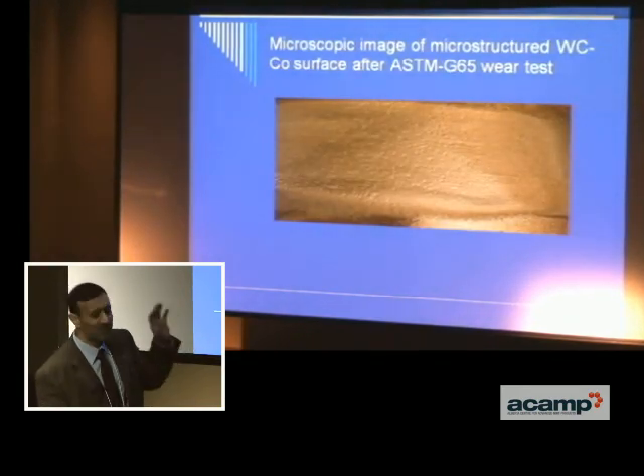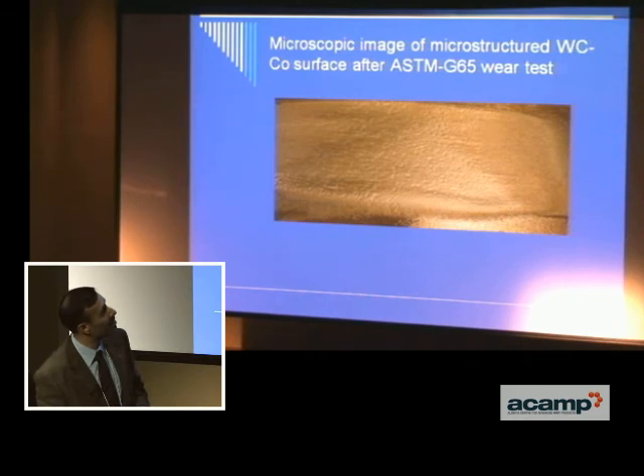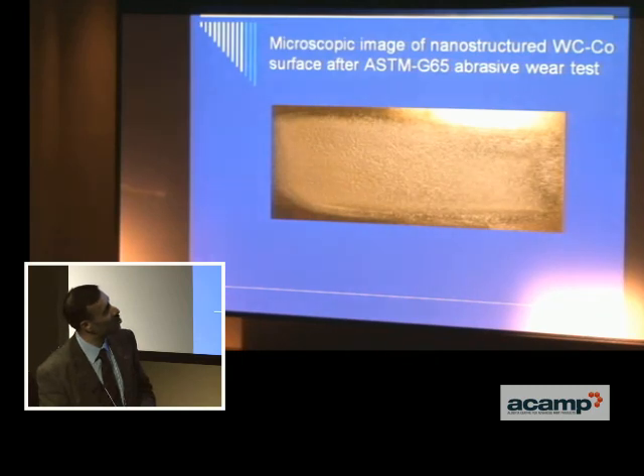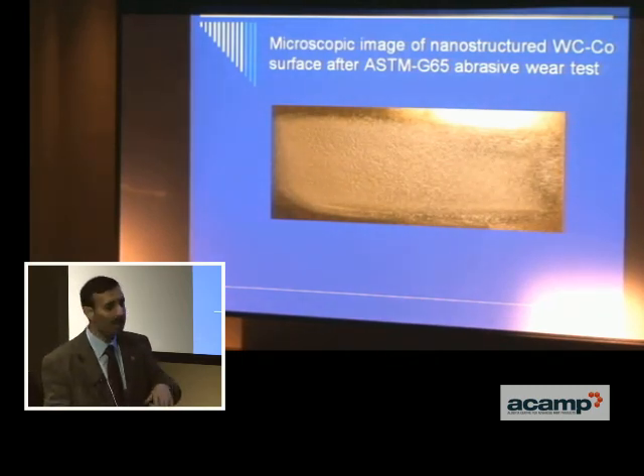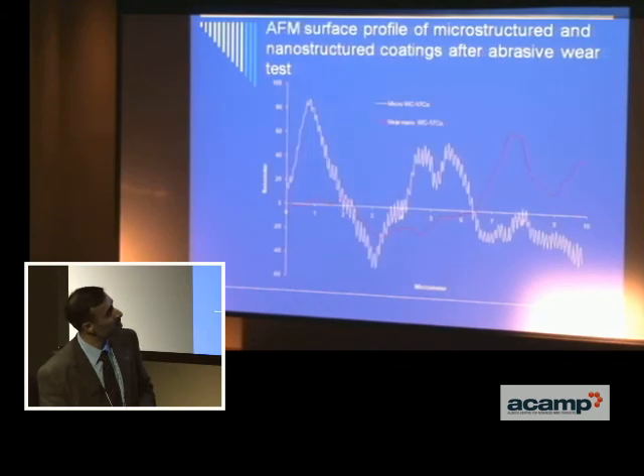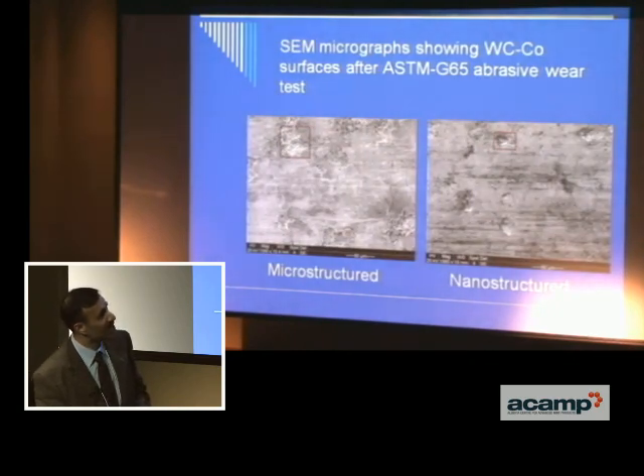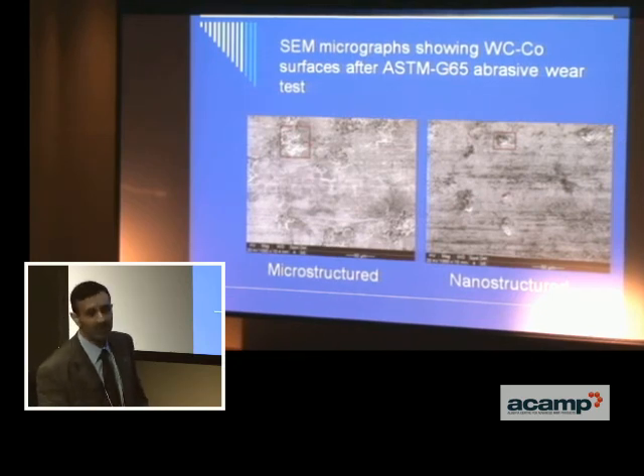So this is a measure of some of that fracture toughness. It's looking at the wear mechanisms. When we compare the surface, we find that this is the nanostructured material, and it's a finer surface finish. When we quantify this using atomic force microscopy, the red line indicates the surface roughness taken from the nanostructured surface, and the white lines indicate the microstructured coating. When we examine surfaces closer to see what the mechanisms are, we find that these pit markings are much larger for microstructured and much finer for our nanostructured.